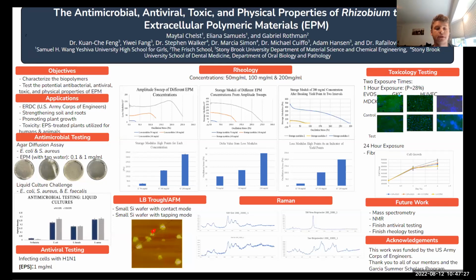Our project is heavily focused on characterizing the EPM and how and why it affects the soil in the overwhelmingly positive way that it does. In order to determine this, it is essential to learn the rheological properties of the EPM. A number of tests were conducted using a rheometer, and we concluded that the strength of the EPM increases exponentially with concentration levels, as can be seen by the amplitude sweep graphs and the bar graph showing the highest point of modulus for each concentration.